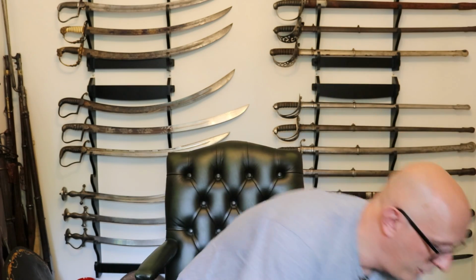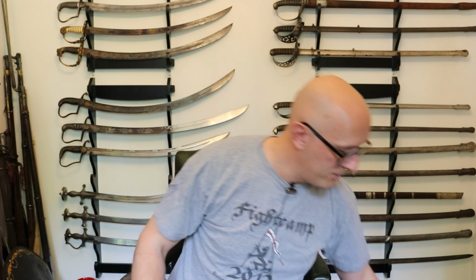If I go to a different option here, the Nepalese kukri, some blades are heated up to that quenching temperature and then have water poured along their edge, and you can still see people today in Nepal hardening the edges of kukris by using a teapot, which I love, to pour water along the edge here. So they are just hardening the edge and leaving the back soft, because that's what you need with something that's really fat and thick, like a kukri, or indeed something like an axe. Just quench the edge.